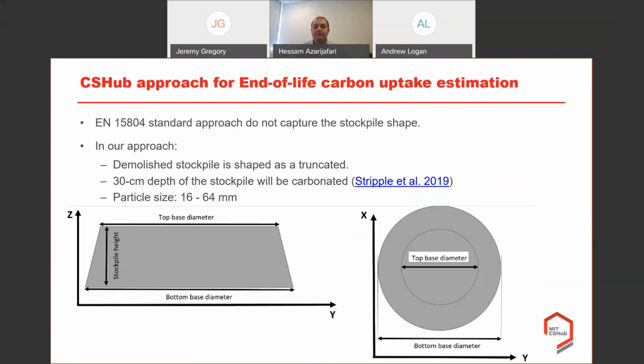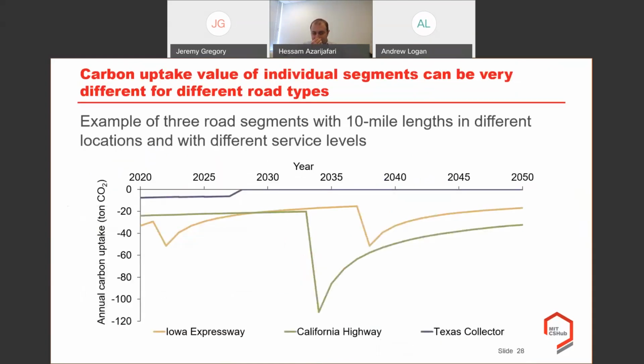And based on the experimental results that we could observe in the literature, only the 30 centimeter depth of the stockpile can be carbonated. In other words, only this part of the stockpile can be carbonated, and the particle size, like I said, for recycled concrete can be from 16 to 64 millimeter. So let's go see the results here.